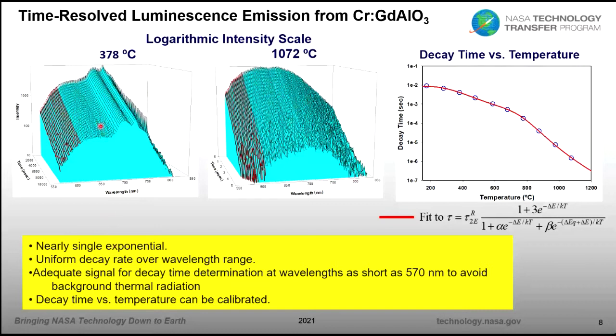You can also see that at each temperature, the lines are parallel. That means you're having a uniform decay rate all across that spectrum. So you can pick any portion of the spectrum. Here's the broadband, and at the lower temperature, you can still see some of the sharper R line, but because of the equilibrium between the states, they all give you the same decay rate, so you can pick any part. Again, when you have going to high temperatures, we pick just this part shaded in red, even though it's not at the maximum, so that we can stay away from the strong background.